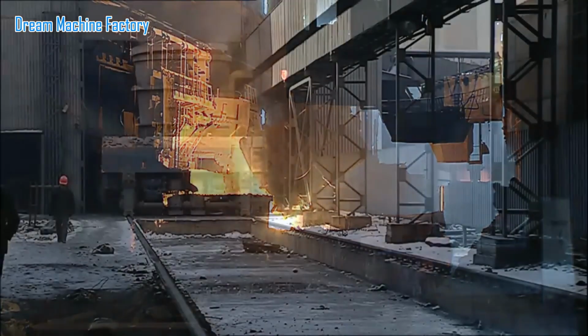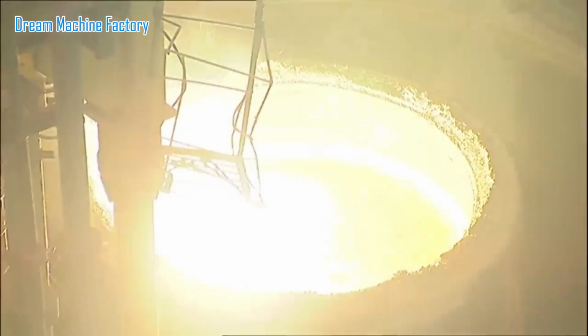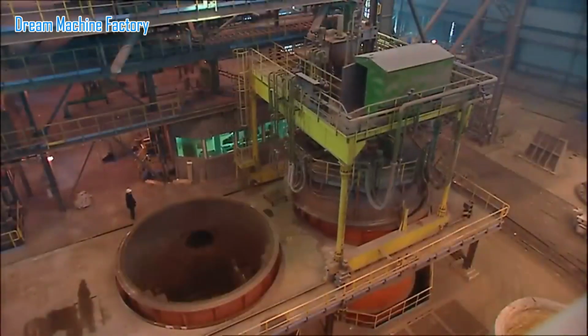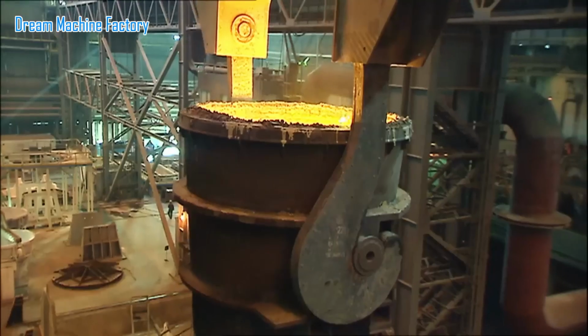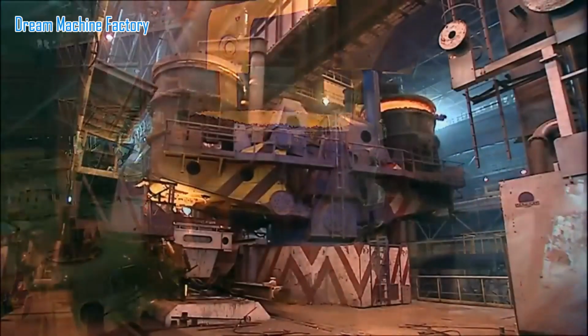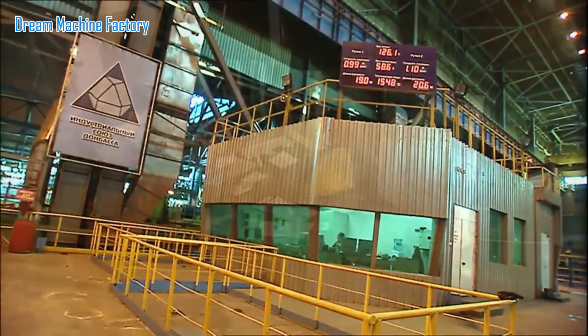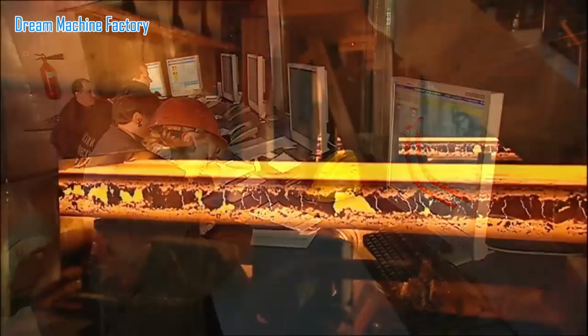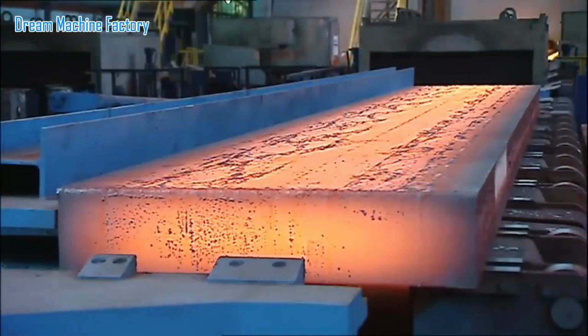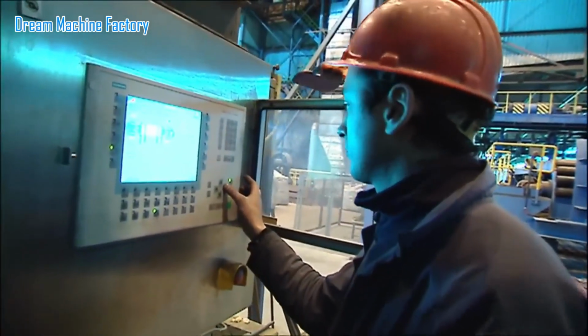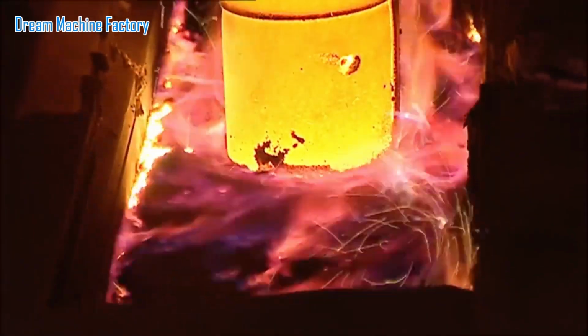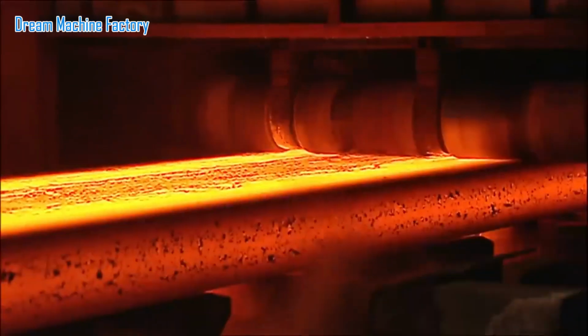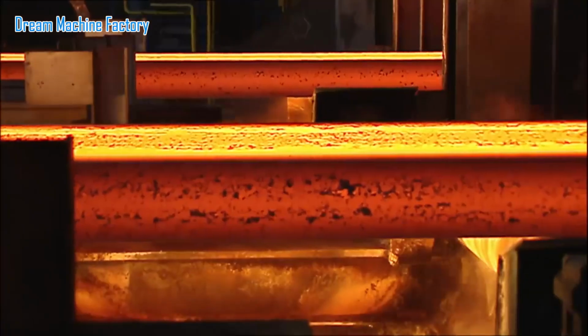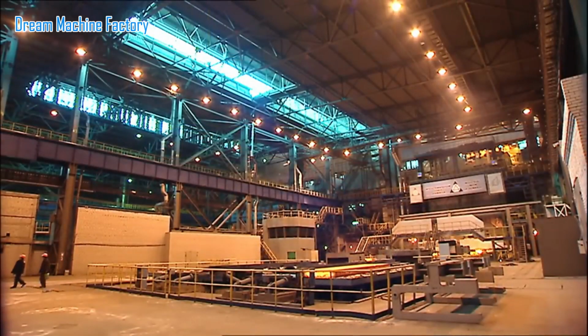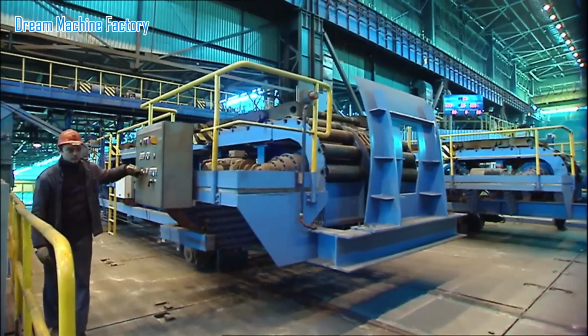Erection of the first support structures for the casting bay commenced soon after, and within a tight project timeframe of just 17 months, the first slab was successfully cast in August 2005. Shortly after, the second slab caster was brought online, further enhancing production capacity. Primetals Technologies oversaw the entire project under a service contract that ensured fast, efficient, and uninterrupted implementation, minimizing disruption to ongoing steel production. The continuous casting line included advanced features such as a twin-station ladle furnace for adjusting steel composition and temperature, and vacuum degassing capabilities for higher purity when required.